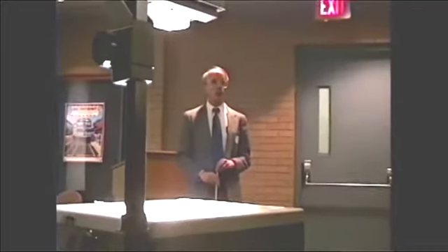Now, the question then that remains is what happens if we try to do a regeneration? Do we make the tetragonal form from the regeneration process? And I can't tell you the answer to that. What I can tell you is that we tried the experiment, but the butane that we were using had some olefin in it, and we produced coke on the catalyst. And the catalyst died, and the coke was thick enough that we couldn't tell whether we'd made the monoclinic form or not. When we did the regeneration, we indeed had tetragonal zirconia at the end, but I can't tell you at this point whether that regeneration just burned coke off the catalyst or whether it actually underwent this transformation.